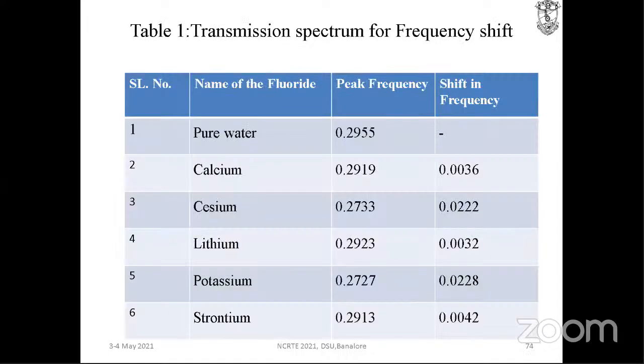Next. You can see for pure water, the peak frequency is 0.2955, but for calcium, it is 0.2919. If the water is contaminated with calcium, you are going to get a shift in frequency of 0.0036. Like that, for potassium fluoride, the peak frequency is 0.2727. That is the potassium fluoride signature, and the shift in the frequency is 0.0228. Because of the shift in the frequency, we will also get a shift in the wavelength, because wavelength and frequency are related.